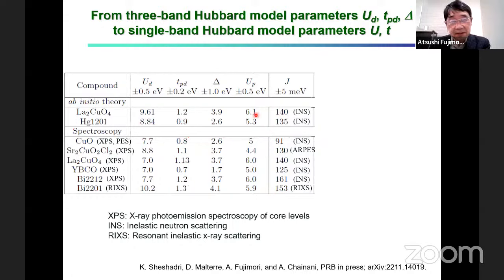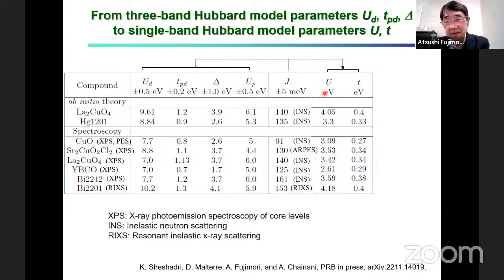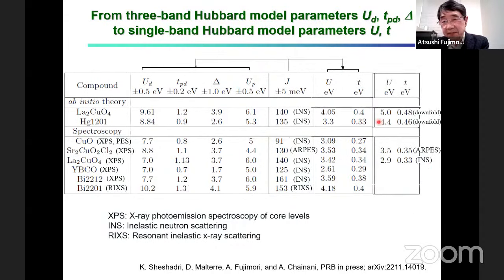ab initio band downfolding into three band, and spectroscopy, XPS and resonant photoemission, and exchange coupling, mostly from inelastic neutron scattering. Combining this, we get U about 3 to 4 and T around 0.3 to 0.4. And we have an independent value from theory by downfolding into one band model and well accepted value from ARPES and inelastic neutron scattering.